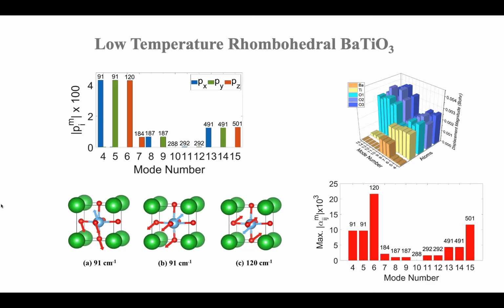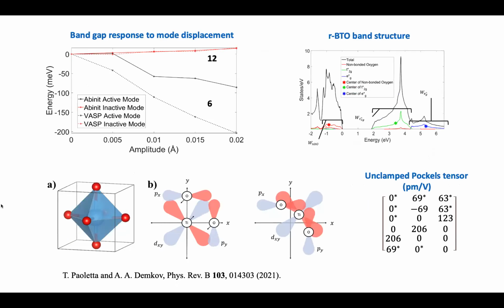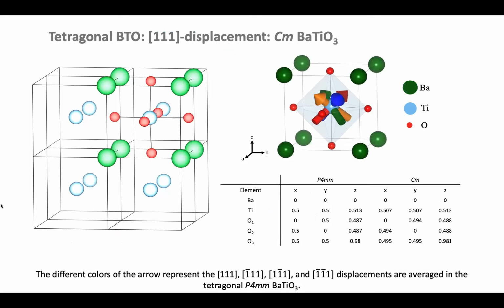And so let me skip it quickly. So essentially, you're changing the hybridization. So you can see that in the inactive Raman mode, you move the atoms, nothing. I'm checking the band gap because it's the smallest transition. In the Raman active mode, your band gap changes quite a bit because it's the titanium oxygen splitting. So we think we understand, we got the numbers, it's all working, but I want to know the tetragonal phase. And that's a real problem.